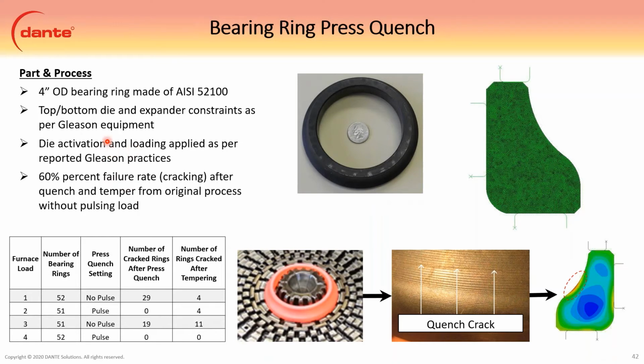All of this was per Gleason practice. So we worked with Gleason on this. They're a manufacturer of heat treat equipment. Do a lot in press quenching. They were getting almost 60% failures from the original process without pulsing. So pulsing essentially relieves pressure of the upper die, which then allows the part to shift. Without releasing the load on the upper die, it constrains the part too much.